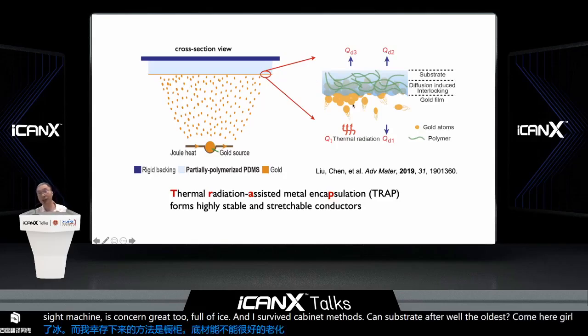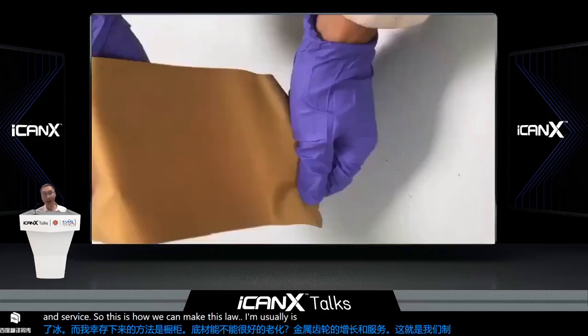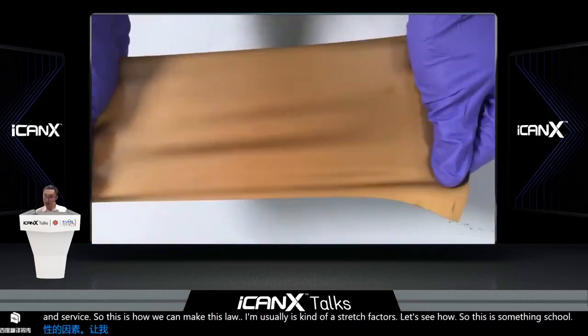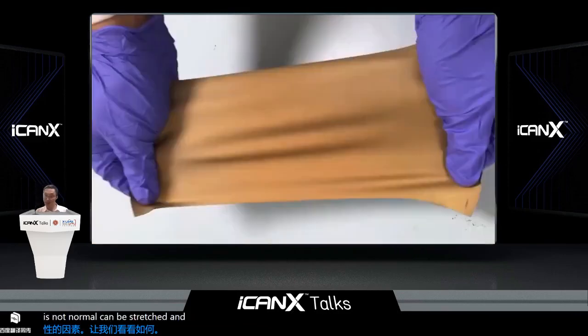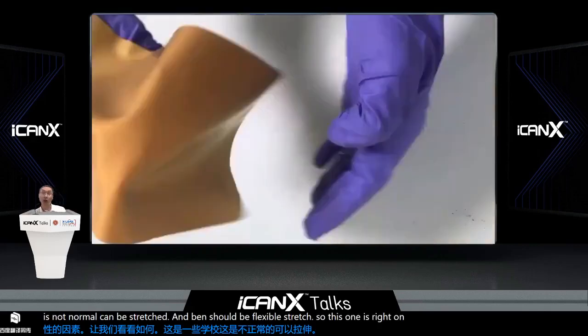And then after a while, all the polymer will fully polymerize, and the metal will continue to grow on the surface. So this is how we can make this kind of novel and unusual stretchable conductor. Let's see how it looks. This is gold, but it's not normal gold. It can be stretched, bent, flexed, and so on. This is a very unusual method. So we call it TRAP: metal was trapped in the PDMS.